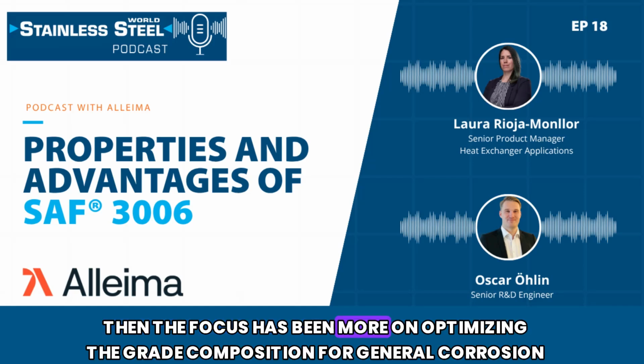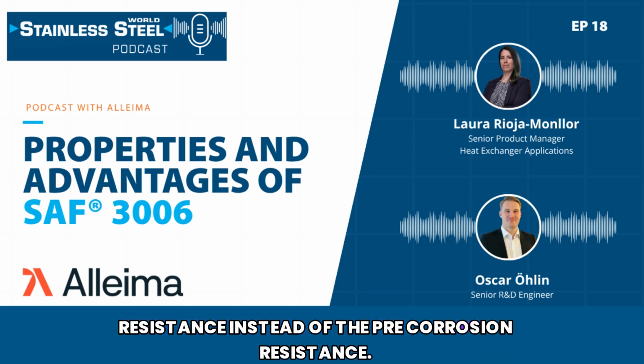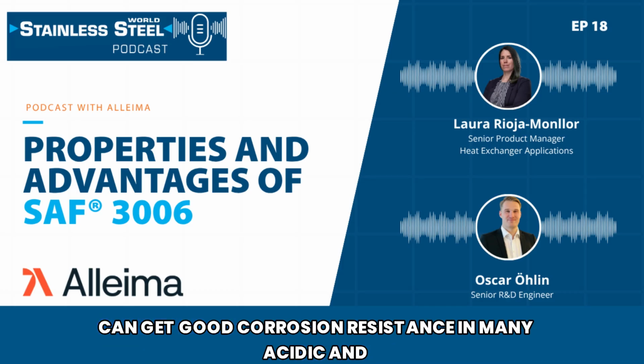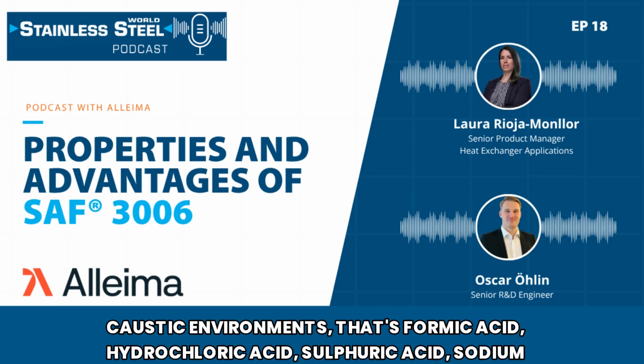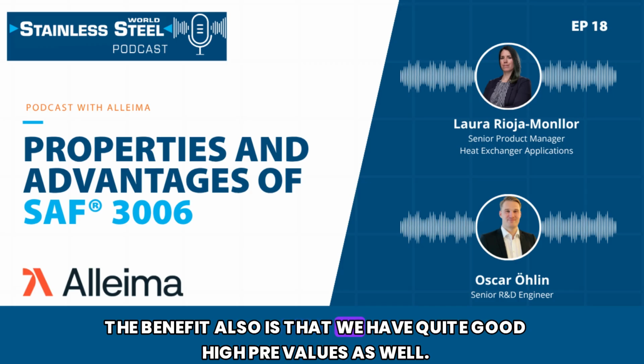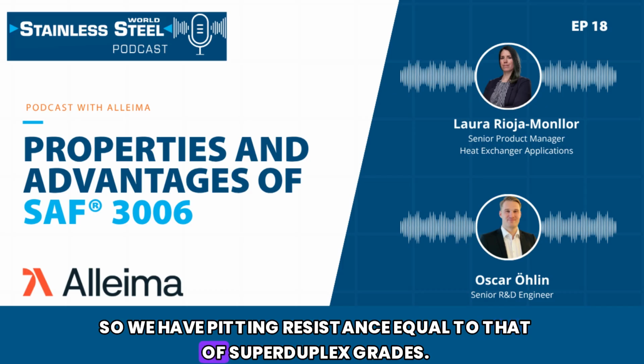The focus has been more on optimizing the grade composition for general corrosion resistance instead of pitting corrosion resistance. And this, of course, gives 3006 benefits over the traditional duplex space, where we can get good corrosion resistance in many acidic and also caustic environments, such as formic acid, hydrochloric acid and sulfuric acid environments. The benefit also is that we have quite high PRE values as well, so we have pitting resistance equal to that of a super duplex grade.